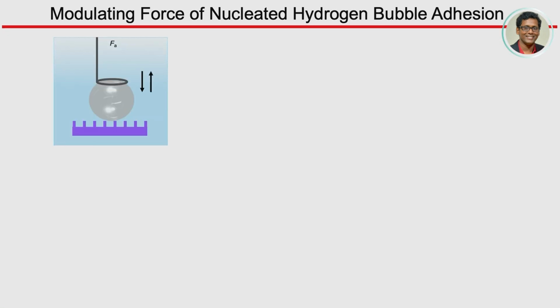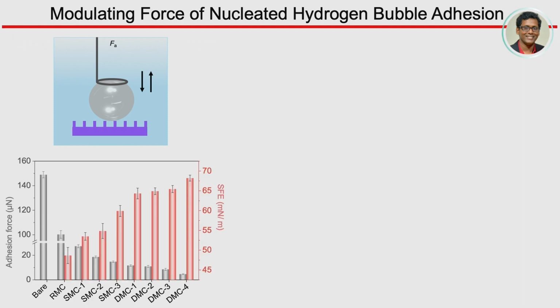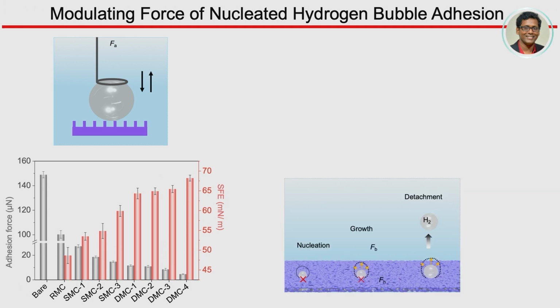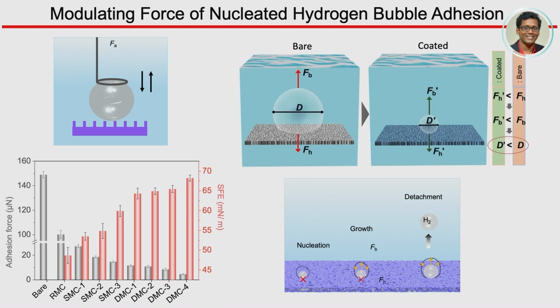And when we put a static bubble and measured the bubble adhesion force with these differently modified interfaces, we can see the force of bubble adhesion gradually decreasing, and the surface free energy gradually increasing. So the higher the surface free energy, the least the force of adhesion. Based on this particular study, we thought we were in the right spot, so we studied these nucleated hydrogen bubbles, their growth, and how they can easily detach from these surfaces.